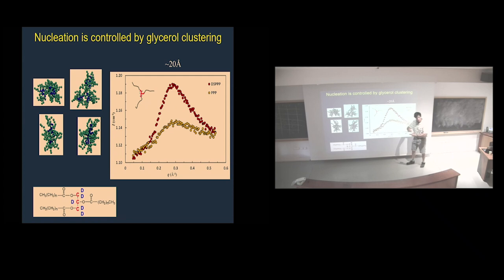And then we put the deuterium, and look, because of scattering length density effects, right? You get a massive increase in the scattering when we put the deuterium in there. So hence, again, that particular structure was related to the glycerols that were hanging out together. You see they're there. And then I'll show you, look at those. Those are some simulations we did. Giuseppe Milano from Italy is our collaborator.